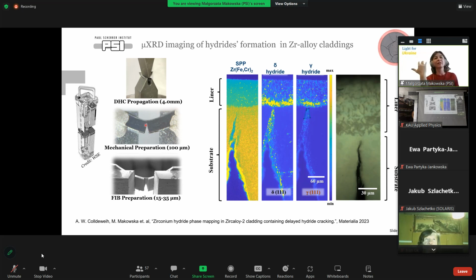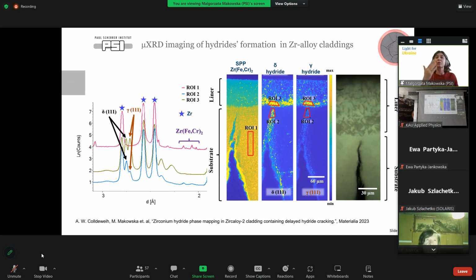And we were studying the distribution of hydrides. So here we could perform this mapping of different types of hydrides. Based on diffraction contrast, we could see that we have two different types of hydrides, which before was not clear. People believed that one of them is metastable, but actually we can see that it stays in the structure.